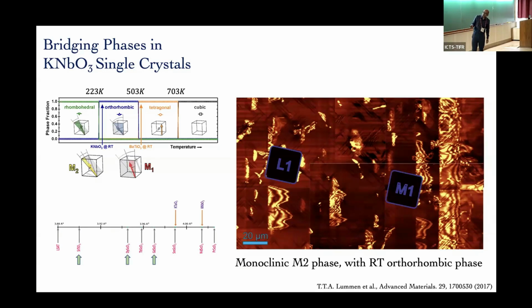My student Sankalpa Hazra, who is from IISc. Thank you, Middey. He worked with you, in Srimanta's lab. And he went and grew these films on various substrates. These are various candidate substrates plus strontium titanate. Potassium niobate is over here. He grew it on 3 of these substrates. And what does that do? You epitaxially grow on something with a different lattice parameter. So in this case, a smaller lattice parameter compared to potassium niobate, right?